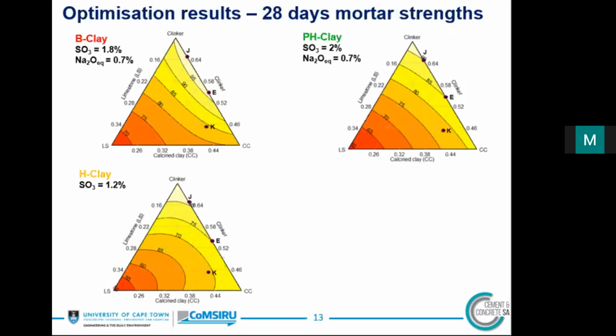Now, this system requires adjustment of sulfate and alkali content. Sulfate is adjusted due to the filler effect of the added supplementary cementitious materials, in this case, calcined clay and limestone. And to get the full benefit of the reaction, of both silicate and aluminate phases, adjustment was done by ensuring that the aluminate reaction peak occurs shortly after the silicate reaction peak, and between 13 and 18 hours. That was done using an isothermal calorimeter available in our lab. And alkali content is adjusted to increase the early strength, but at the same time ensuring that the long-term performance of the mix is not affected. Literature suggests a value between 0.6 and 0.8%. In our case, we decided to select 0.7%.